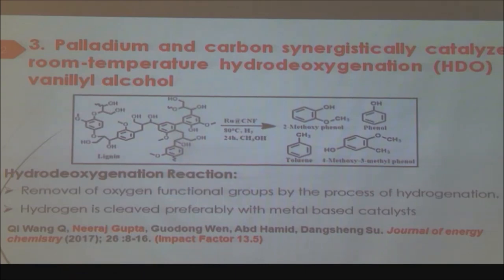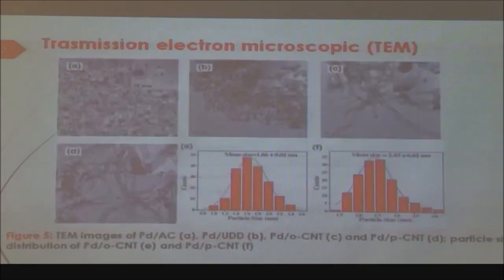Though these days we are working in this direction also, I'm not going to discuss it. I have done one process where we have achieved metal-free hydrogenation also, but that's not a part of this discussion. I'm not going into that detail, because doing metal-free hydrogenation is a very, very challenging task. So in order to do the initial work, we choose a metal, ruthenium and also palladium. We choose these metals and deposit nanoparticles of these metals onto the carbon surface, and then we perform the hydrodeoxygenation reaction. I'm going to discuss two such strategies in this work. The first work is where we have used palladium.